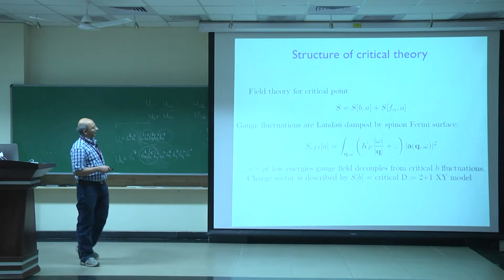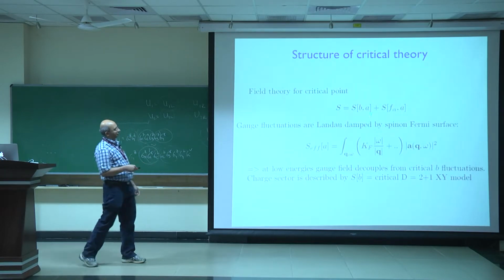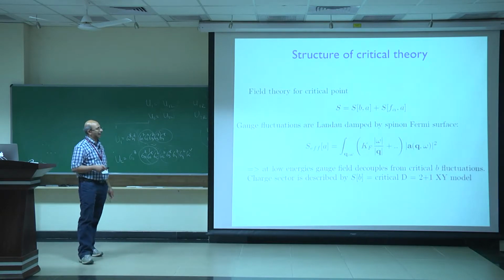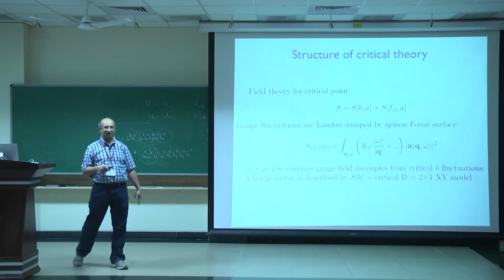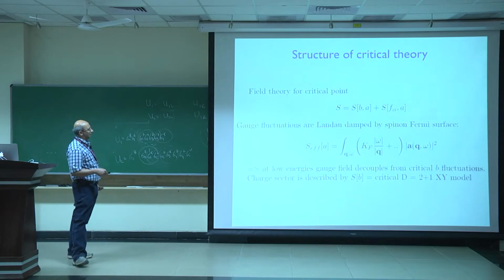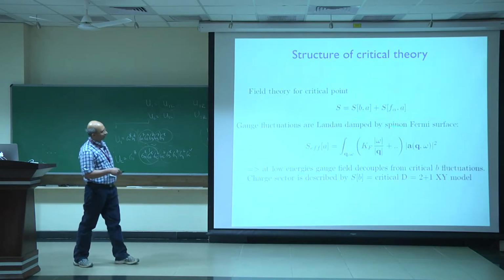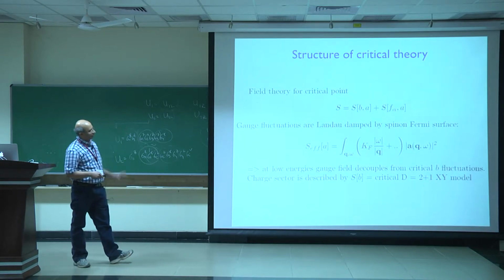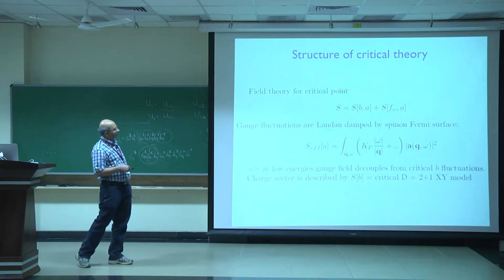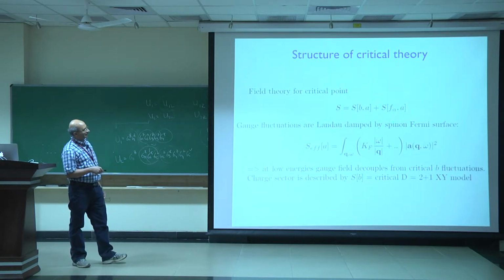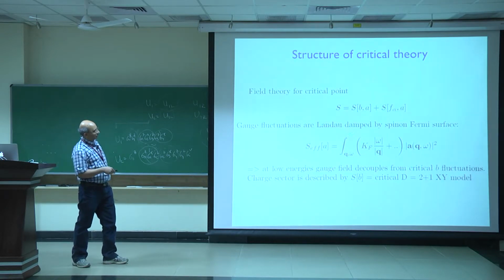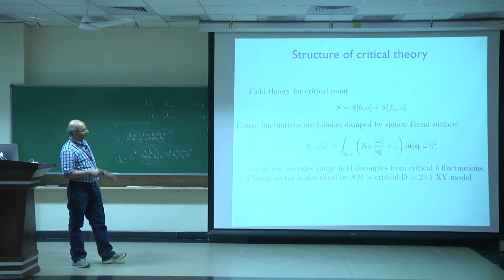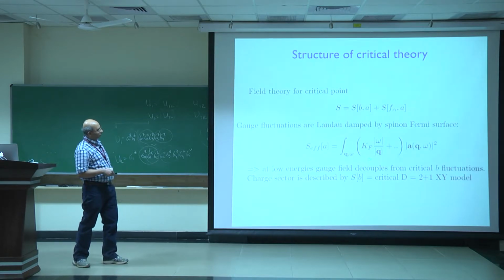And the first thing is to recognize that because of the coupling to the Fermi surface, there's a phenomenon known as Landau damping of the gauge fluctuations. What this Landau damping means is that the effective action for the transverse portion of the gauge field, usually we don't need to worry about the longitudinal portion of the gauge field in a problem like this, it's screened by the Fermi surface. So the transverse gauge field has a term which for imaginary frequency looks like mod omega over q.